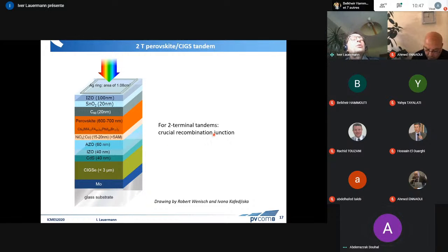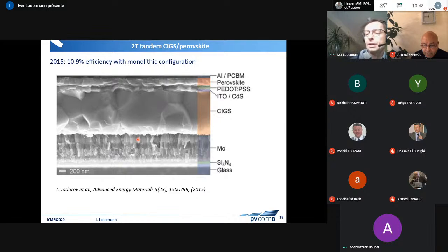We are going for the 2-terminal device. So we have the substrate, we have the bottom cell, CIGS, we have our transparent conductive material at the top of the bottom cell. And here we have the top cell, the perovskite, with this fairly complicated composition with the right band gap. And now the light passes through the top cell, reaches the bottom cell. Now what's crucial is this interface here between the two cells we call the recombination junction. And this material has to meet certain criteria. Of course, it has to be transparent for the red light, which needs to pass through here. It needs to be electrically conductive. And it needs to have certain other properties. I'll come to that in a moment.